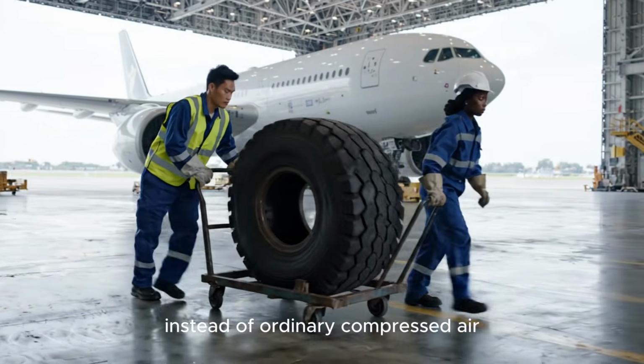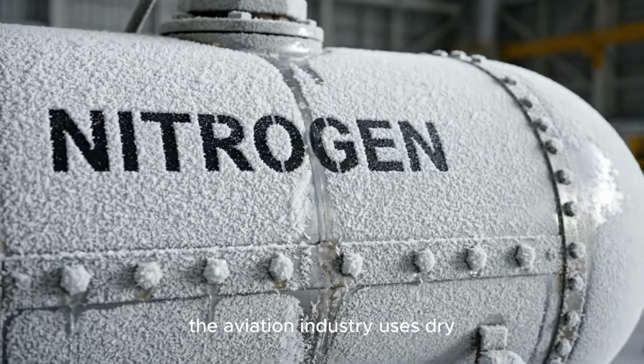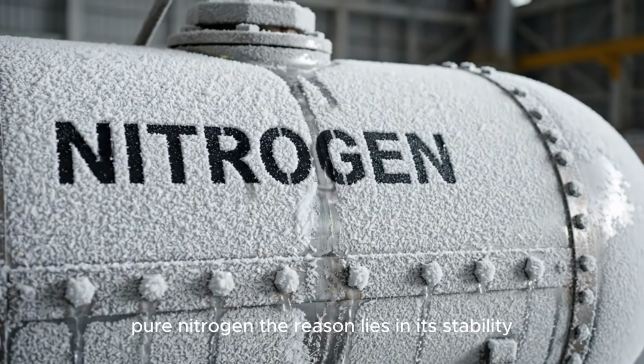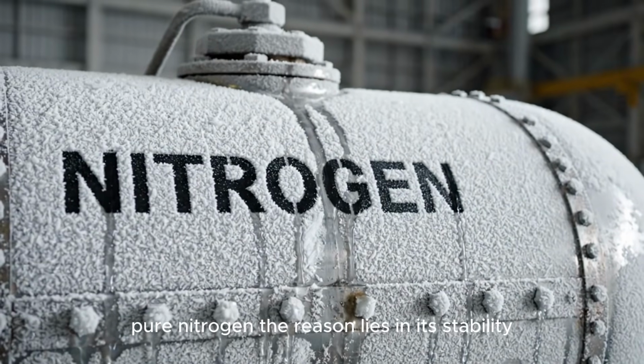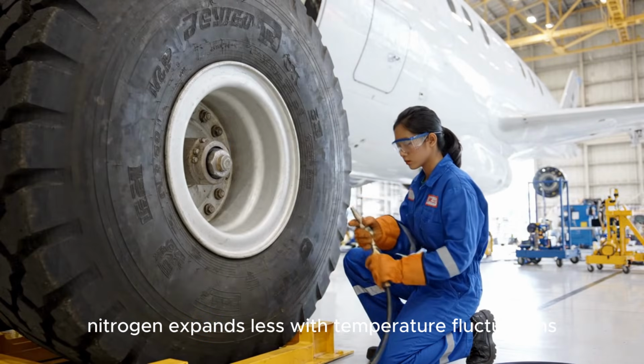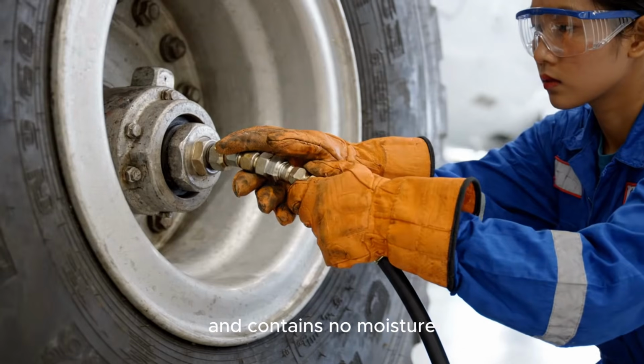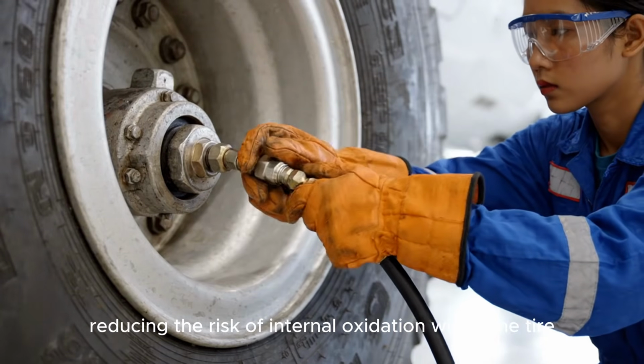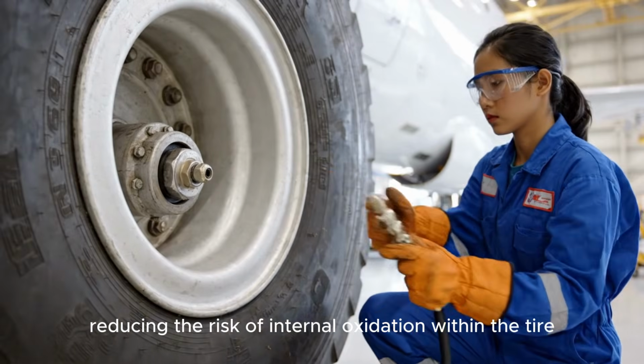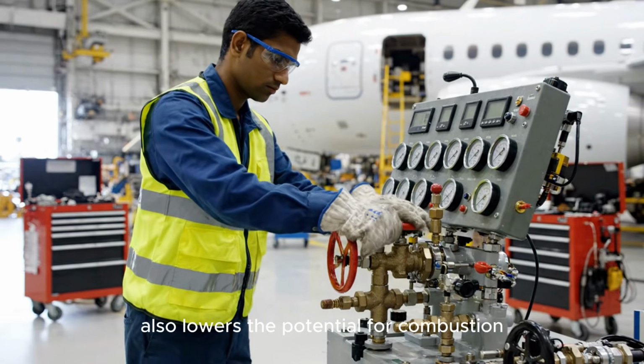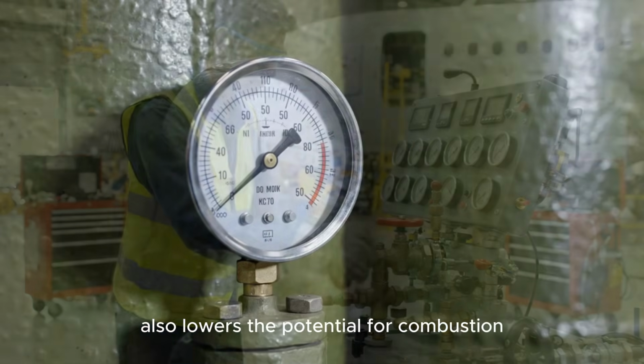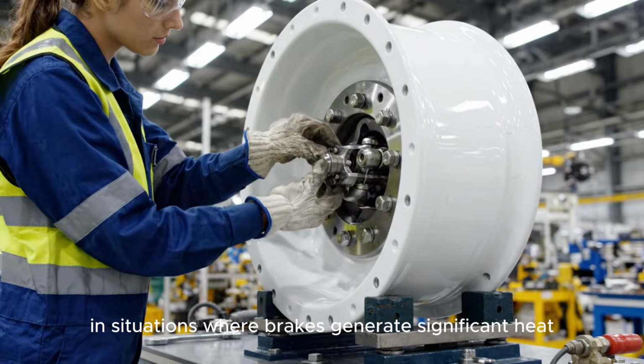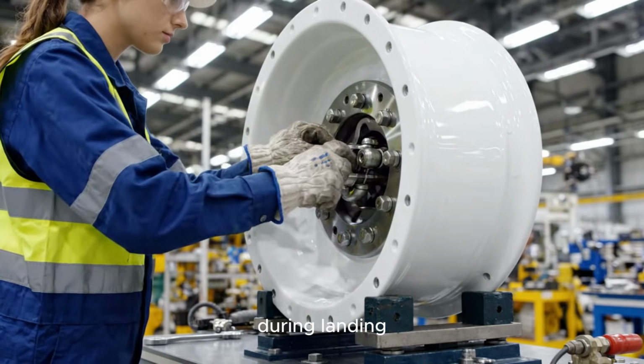Instead of ordinary compressed air, the aviation industry uses dry, pure nitrogen. The reason lies in its stability. Nitrogen expands less with temperature fluctuations and contains no moisture, reducing the risk of internal oxidation within the tire. Eliminating oxygen also lowers the potential for combustion in situations where brakes generate significant heat during landing.